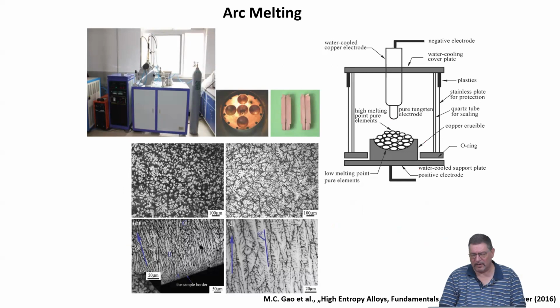You also know? Okay, then I don't need to talk much about it. It's obviously a process which works very well. You just assemble different ingredients. You use a high power electric arc to melt the material while it's situated on mostly a water-cooled copper plate. And then you go through the liquid phase, and once you stop the beam or you take it away, the material freezes again. When you did this yourself, what are the problems with this method?